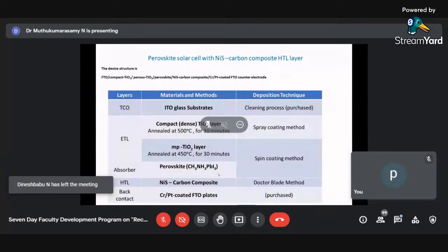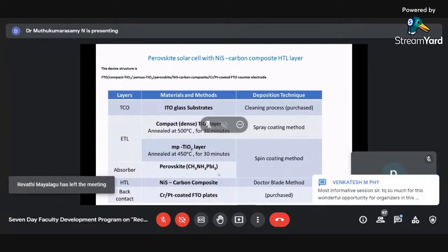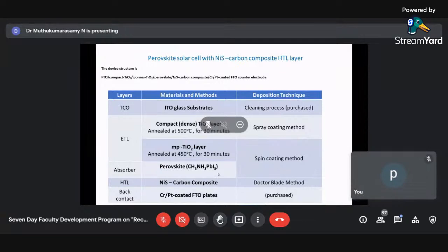These are all the characteristics: X-ray diffraction pattern of the perovskite material, the band gap, all those things we did. And this is the structure of the solar cell which we fabricated. I have also given the methodology which we followed. We started with ITO glass substrate and a compact dense TiO2 layer by spray coating method. Then a mesoporous TiO2 layer with spin coating method. Perovskite material with spin coating method. And I will also tell you how you can prepare the perovskite material in your laboratory itself. Then nickel sulfide, carbon composite by doctor blade method, and chromium platinum coated FTO plates, which were purchased, were used as the counter electrode.